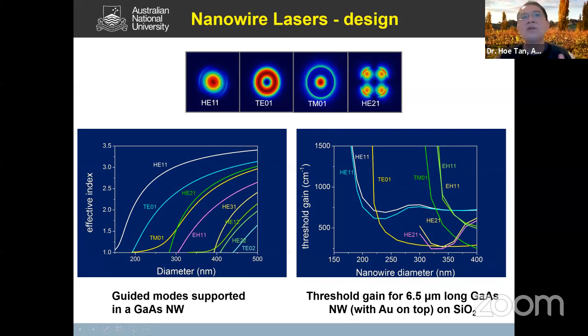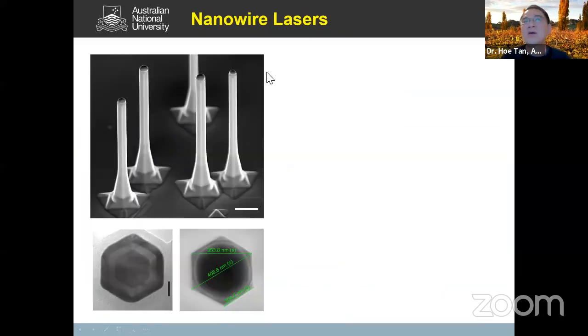So that is very easy to do. What we have to do now is just get the appropriate gold particle of the right size, and then we can grow this gallium arsenide nanowire. And that's what we did. We used a larger diameter gold particle, and then we grew this gallium arsenide nanowire. As you can see here, this is a cross section.